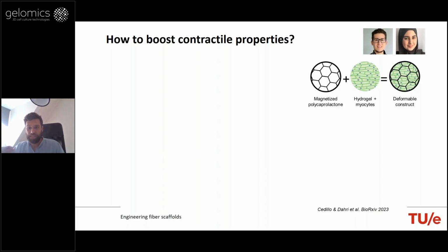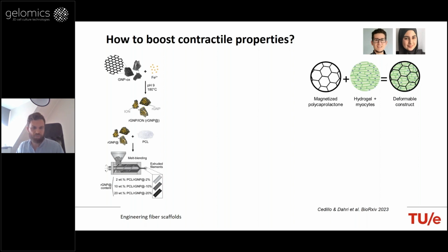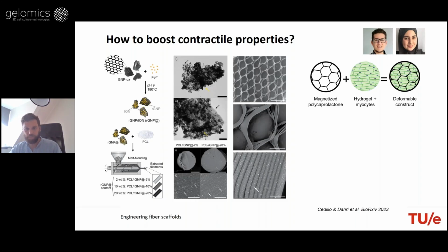To do that, we looked again at the hexagonal microstructures, and then we explored reduced graphene oxide, for the reason that it promotes myogenic differentiation, or it's described in the literature to do so, and has a low reduction in cell viability. But as we know, reduced graphene oxide is not magnetized. So what we explored first was to investigate how iron could be oxidized in the graphene nanoplatelets. And it was very interesting to see that through the chemical process, we could in situ deposit iron oxide nanoparticles on reduced graphene oxide. And they were homogeneously distributed in these particles.